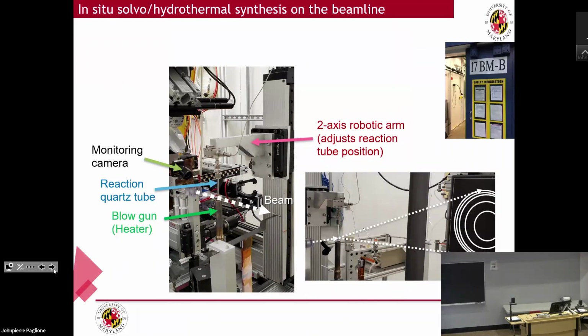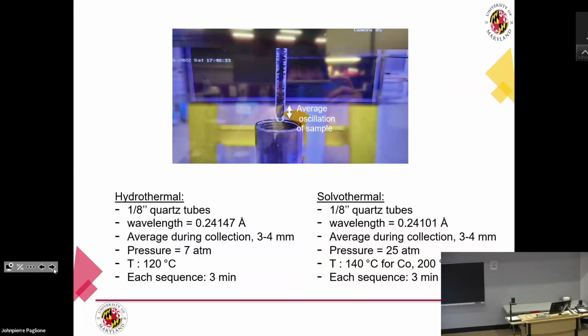So what we do is in situ hydrothermal solvothermal synthesis on the beamline. We go to the Advanced Photon Source, and actually we don't have anything fancy like Dermot O'Hare's setup with sapphire windows or anything like that. We just put in a little quartz capillary tube, and we backfilled it with helium. We got to 7 bars of pressure, and we start with our reagents, and we're able to watch these diffraction patterns in seconds and see how the hydrothermal reaction proceeds. And so these are the conditions for hydrothermal. You can see the quartz tube sizes, the pressure that we use, and the temperature.